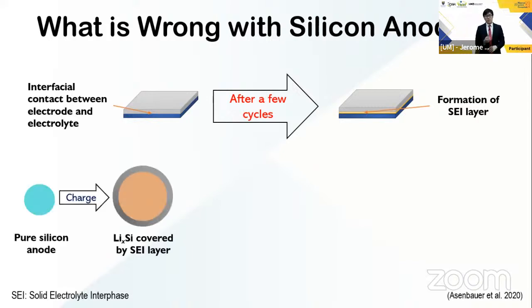The problem of silicon lies in its massive volumetric changes during charging and discharging. When a silicon anode is charged, it expands in size and volume up to 300%, resulting in the formation of a huge SEI layer. And when it discharges, it shrinks back to its original size, and the SEI layer ruptures and gets destroyed. Subsequently, you have lost the protection you just formed between the electrode and the electrolyte.